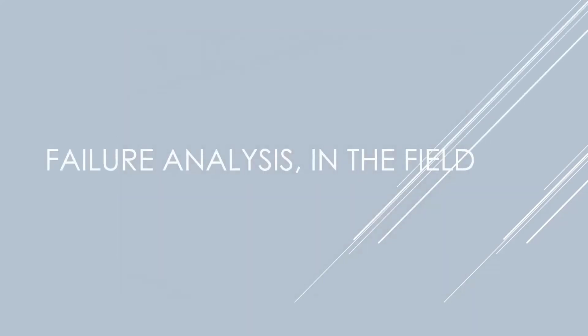So we do failure analysis in the field. This is where we use in-situ replicas, and we're going to be looking at microstructures now. So this looks like a bad skin disease, doesn't it, eh? But this is a microstructure off a reinforcing pad that was welded on a pressure vessel here in Alberta. It had cracked in the heat affected zone of the reinforcing pad. And so they wanted to know, what did possibly cause that?